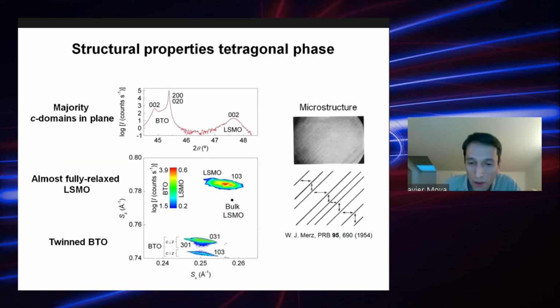If you want to correlate this with the structural information that we have on the substrate, as I said, you need to look again at the X-rays. You see that you have these two different regions where the c-axis is either in plane or out of plane. And this c-axis, by the way, is the direction of the relative polarization in the material.